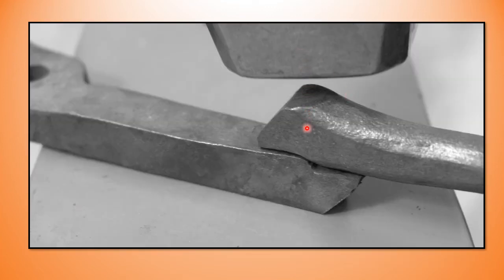Once this is held in place, drop your tongs, pick up your hammer with that same hand. Hit the top and then quickly follow this toe down and blend that in to your bottom piece. If you have time, turn it over and do the same on the other side. If you've lost color or as soon as you lose color, you're going to want to put it back in the heat.